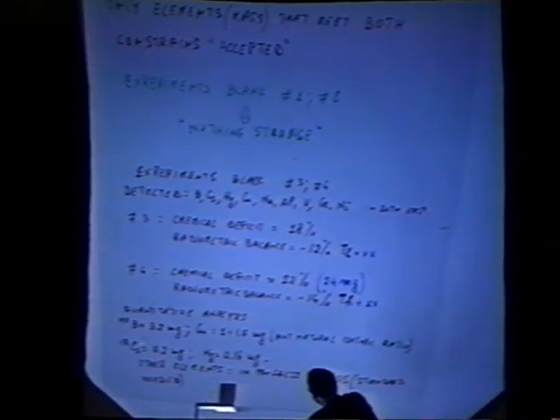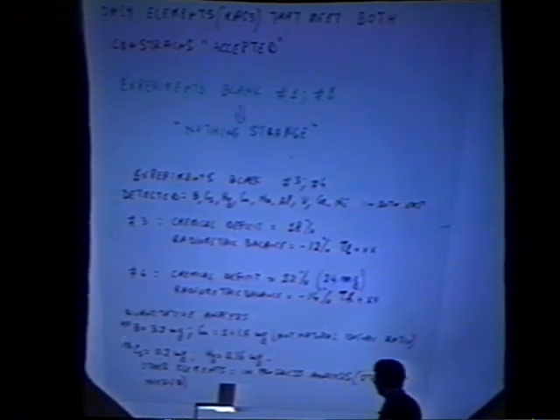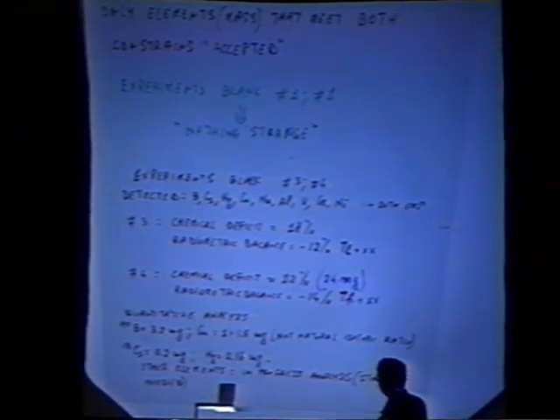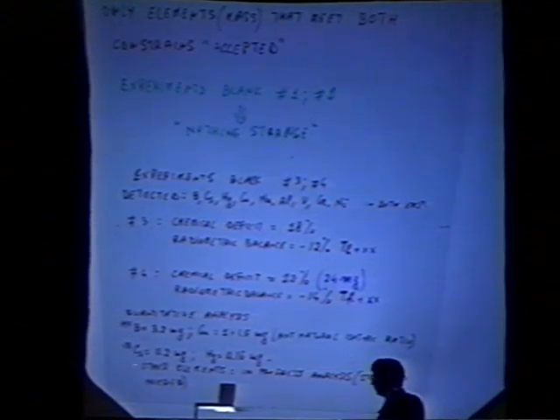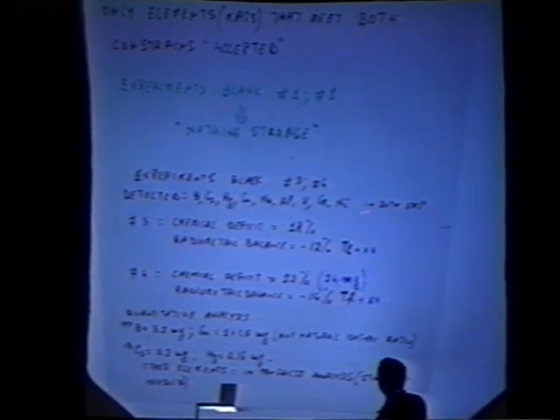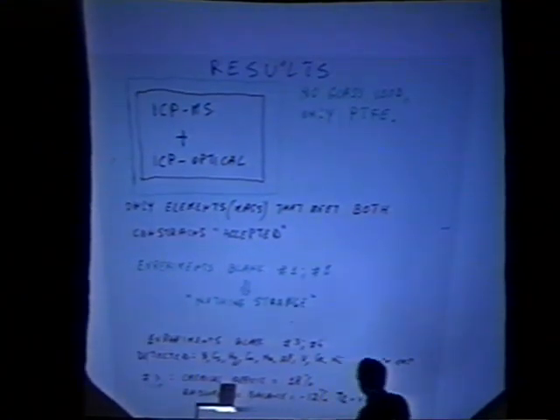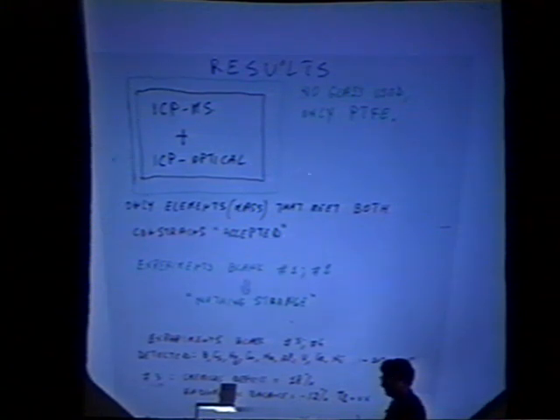The quantitative analysis of the elements detected was, for example, 3.2 milligram, and 1.1 milligram, but the isotopic ratio was not natural. Cesium 133 and mercury. The other elements are in progress. One other important point, because we use strong acid attack, we use only Teflon, never glass.